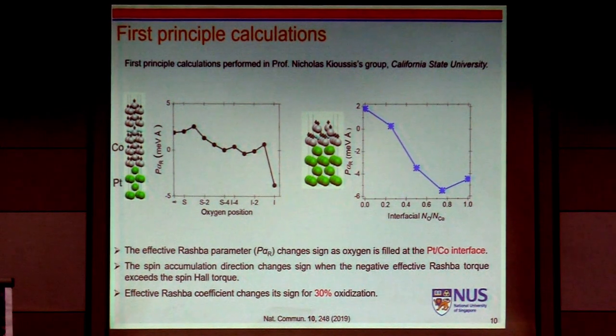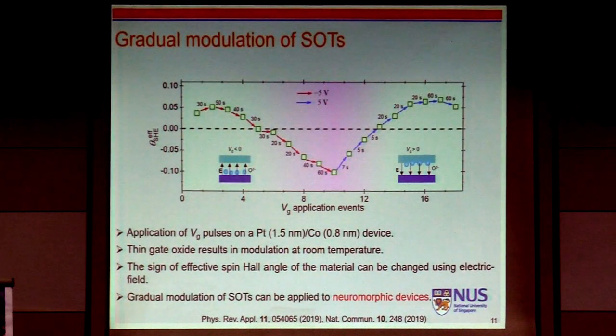And experimentally, there is no way we can put oxygen at a specific layer. So what we are doing is we oxidize the whole layer all together, because it's only 1 nanometer plus or minus. And we found about 30% of oxidation will trigger this sign change. During the operation, we found a very gradual change.